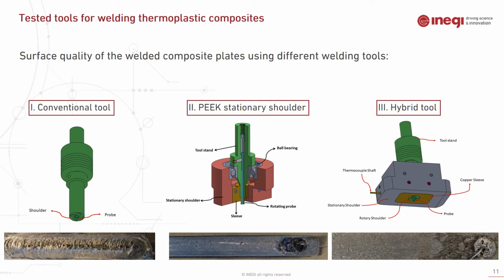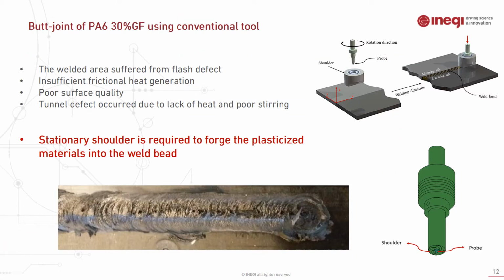This slide shows the surface quality of the welded plates using the three different tool concepts. As you can see, the conventional tool had a very rough surface quality compared to the PEEK stationary shoulder. The PEEK stationary shoulder had the smoothest surface, and for the hybrid tool the surface was rough, but not as rough as the conventional tool. The conventional tool created poor surface quality, also a tunnel defect in the middle of the weld.